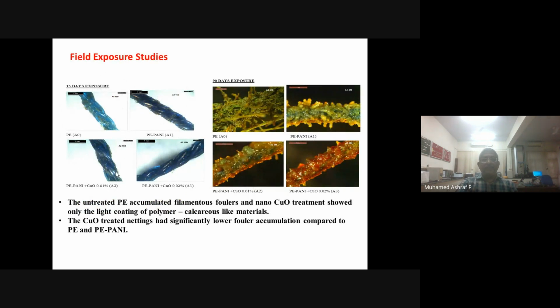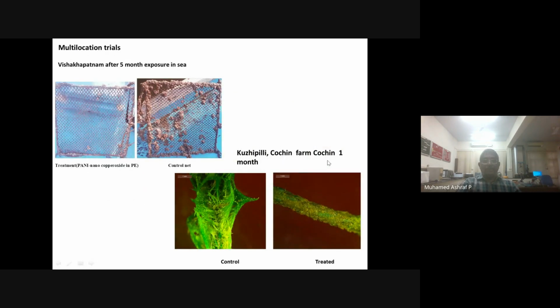And then this material we exposed in the marine environment for 15 days and 90 days, and we can see this is the control. The nano copper oxide treated net has shown very good resistance to the fouls. And this is the real sample we exposed in the Visakhapatnam Sea, and we can see that the control has a large number of different types of fouling organisms, but the treated one is free from everything.